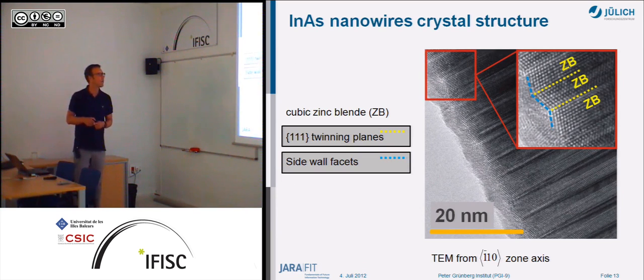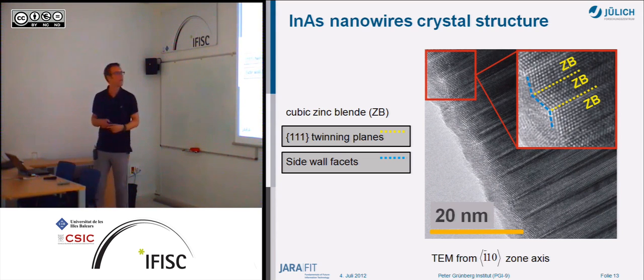The way of growing is slightly different. Here you mainly have the zinc blende crystal configuration, but you have this twinning. So you're switching the ordering of the zinc blende from ABC to CBA, the other way around. And then you have these twinning planes in between.